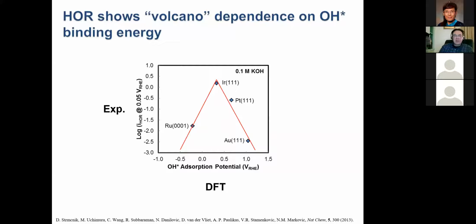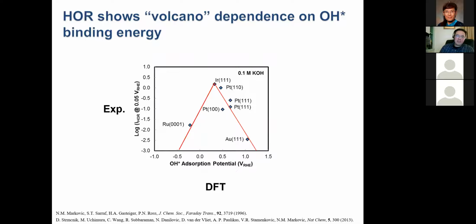And if we start putting all of the known data for the hydrogen oxidation rate in base onto something that looks like a volcano, I think with those 4 points you'd look at me and say that makes a pretty good volcano for the experimental rate of hydrogen oxidation plotted versus how strongly we bind hydroxide on these 111 surfaces. And if you're very convinced by this, I'm worried I can sell you just about anything, because for any 3 points I could have drawn a volcano. So I've got 1 point that happened to fit, if you want to look at it that way. So 4 points can't convince you of that type of relationship very well.